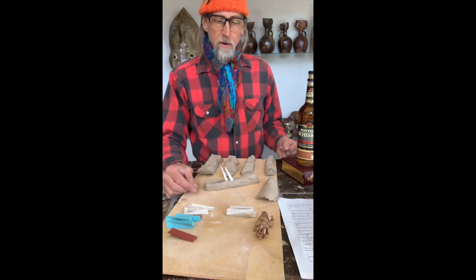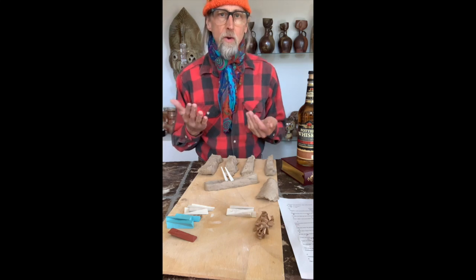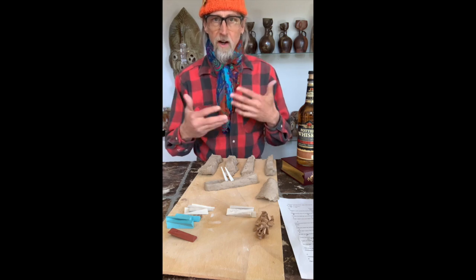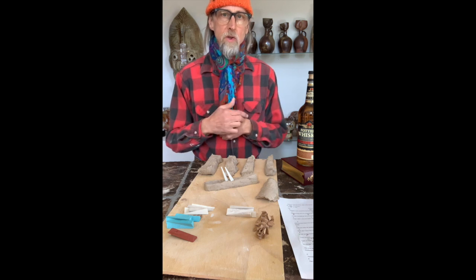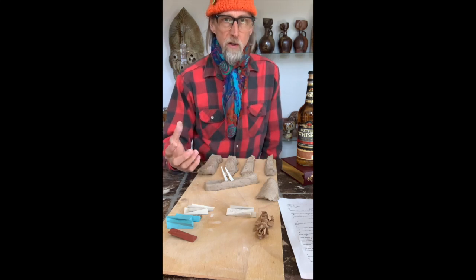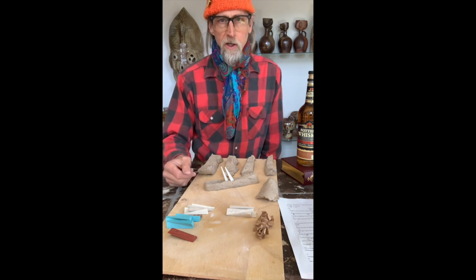The other thing, again, to think about is what cones you use. In this kiln, I don't care about the mid-range temperature, so I'm not going to waste a 5 or 6 or even a 7. Any of those cones, I can see visually where we're going, and I can use a pyrometer to see the climb. But some people choose to use a mid-range cone, and then you better use a boat, because those will turn into glaze at that cone 10 or 11 or whatever your target cone is.